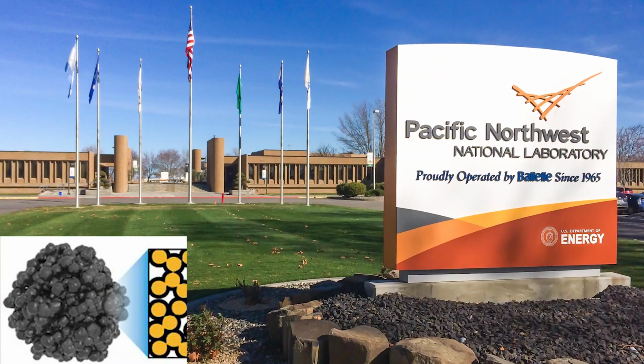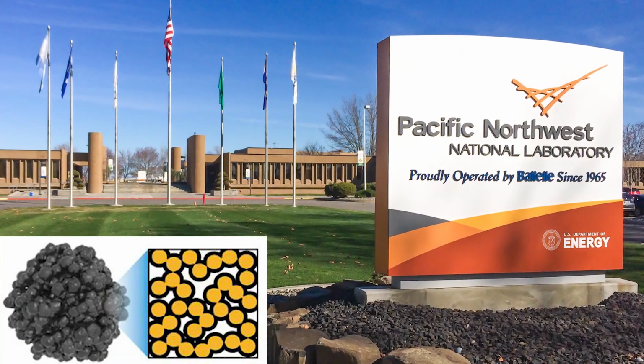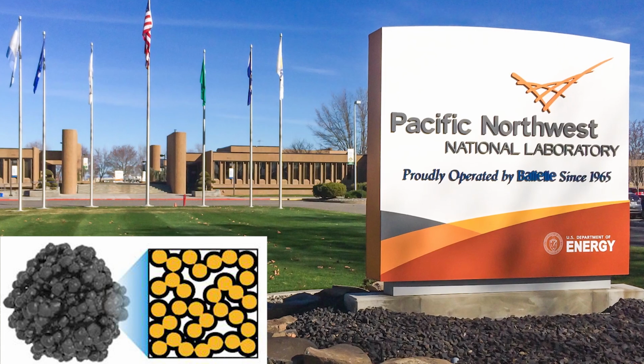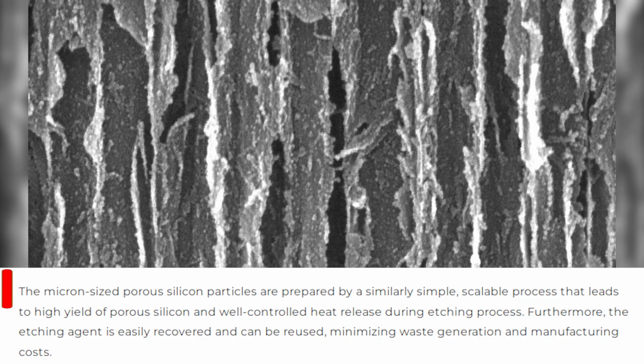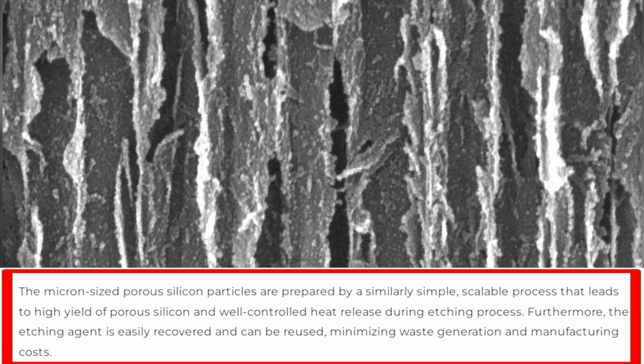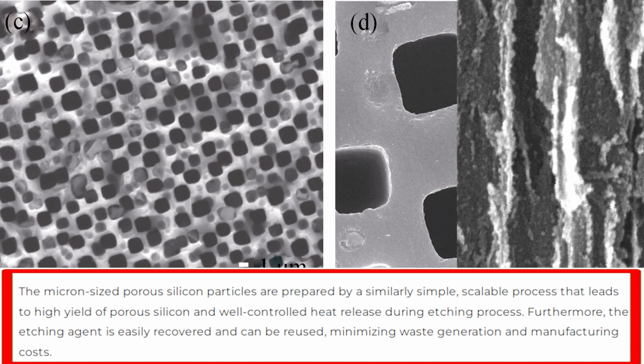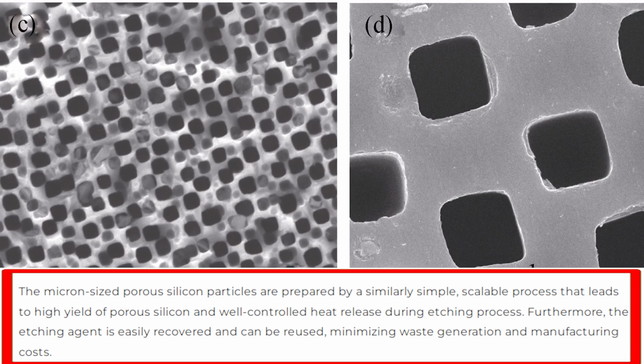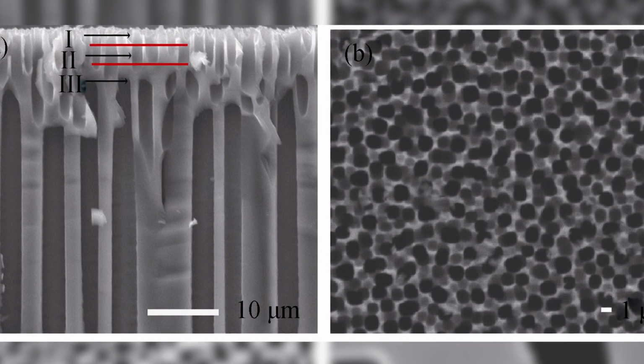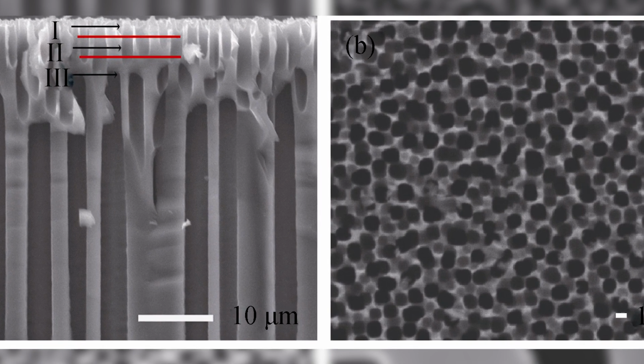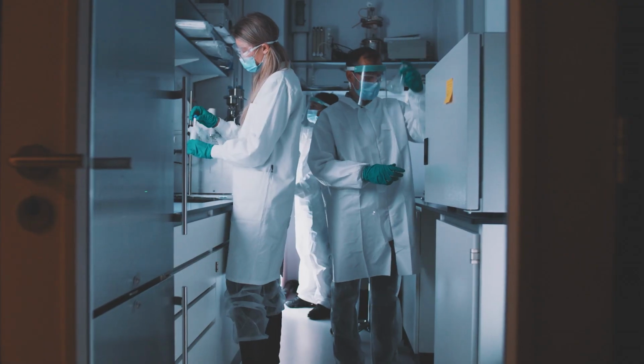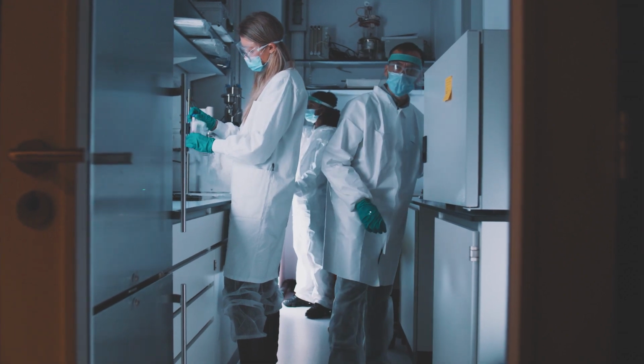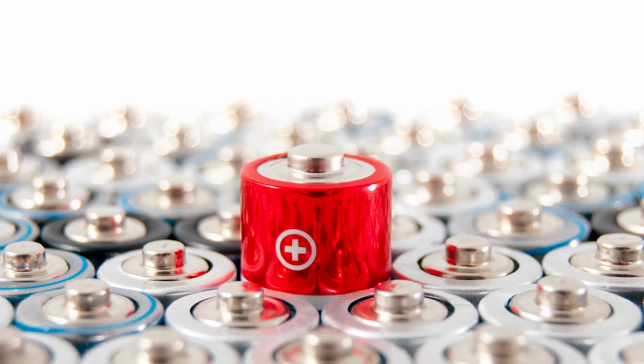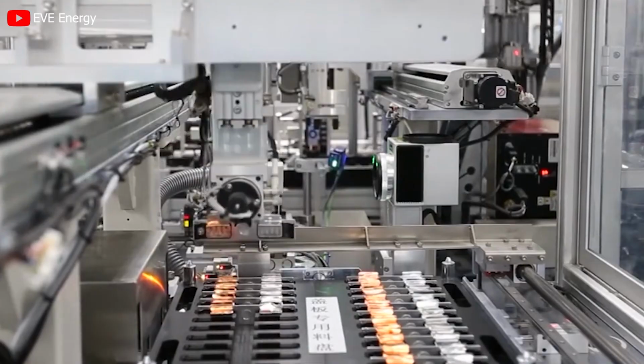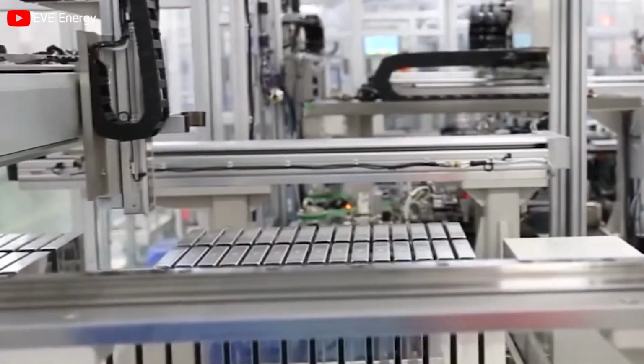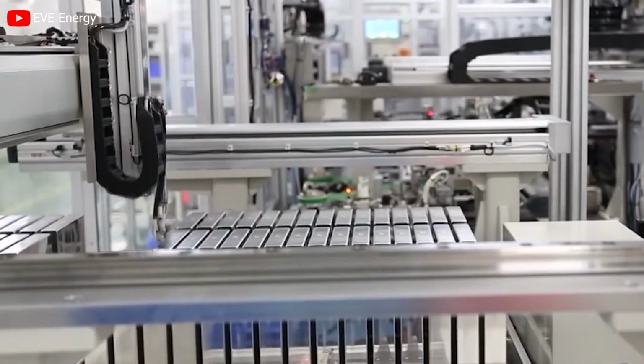The Pacific Northwest National Laboratory team has developed a scalable technique for fabricating micron-sized porous silicon. This process yields abundant quantities of porous silicon while maintaining a consistent temperature during the etching phase. Additionally, this method permits the recovery and reuse of the etching agent. The team has also devised a specialized, high-concentration electrolyte tailored specifically for silicon anodes. This formulation substantially reduces leakage current and extends battery cycle life.